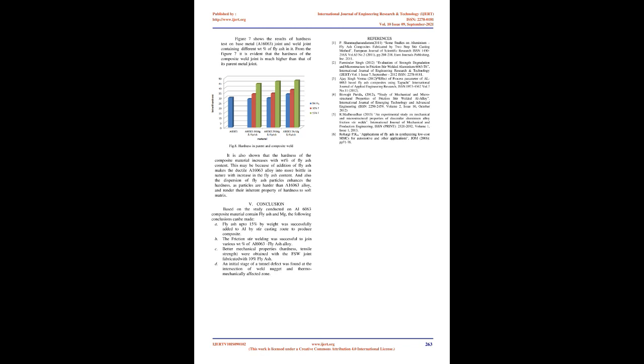From Figure 7 it is evident that the hardness of the composite weld joint is much higher than that of its parent metal joint. It is also shown that the hardness of the composite material increases with wt% of fly ash content. This may be because addition of fly ash makes the ductile Al6063 alloy more brittle in nature with increase in the fly ash content. And also the dispersion of fly ash particles enhances the hardness, as particles are harder than Al6063 alloy, and render their inherent property of hardness to the soft matrix.